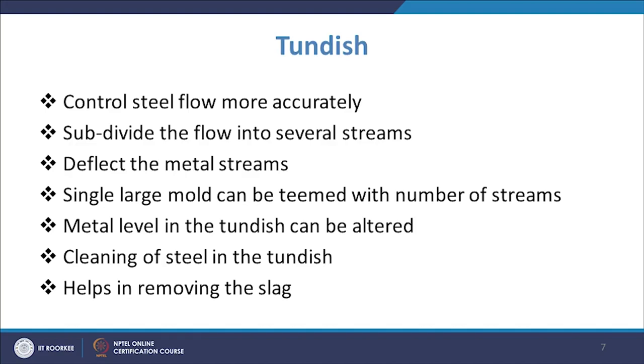Then the tundish will control the steel flow more accurately, because you have the control mechanism, so that a constant amount of liquid steel should fall into the mold. Also, because it has a very large surface area, during the changeover there will be only a very small decrease in the height of the free surface of liquid metal in the tundish. So the change in the velocity will be very, very small. Basically the steel flow will be controlled more accurately because of the tundish.